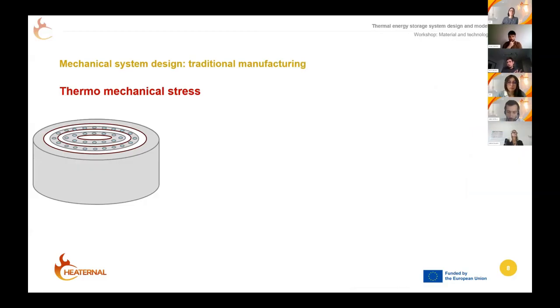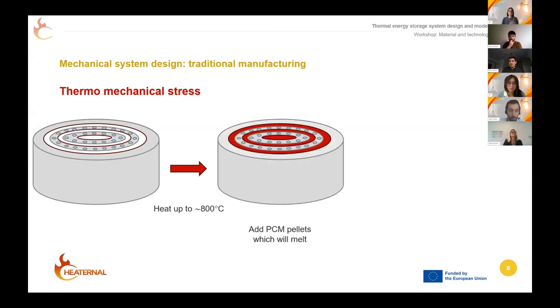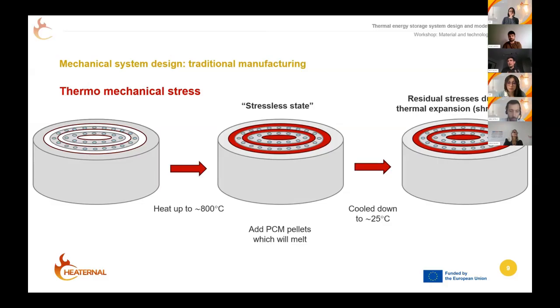This was our thermal problem, so I've shown you how we try to solve these things. The second thing is our mechanical problem, and it's a thermomechanical one, so you get thermal fields and thus stresses. Now, what actually happens is you have a refractory brick, you heat it up to about 800 degrees Celsius, and you add to it PCM pellets, which will melt. And at 800 degrees Celsius, it is in somewhat of a stressless state, it's annealed, and the PCM is liquid. But then the system cools down, and it should be able to cool down to 25 degrees, and you get stresses due to differences in temperature field, but also differences in thermal expansion.